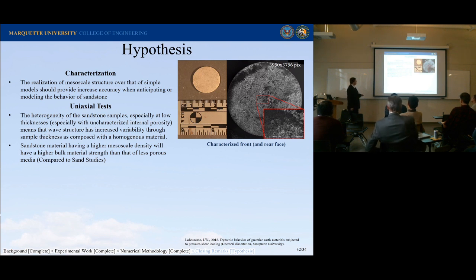I won't make it. And then finally, a sandstone material having higher mesoscale density will have a higher bulk material strength than a less porous media. So we'll see if that's the case as well. If I can do enough pre-characterization, maybe I can see that there's a porosity-strength relationship. But it'll be a lot easier to do than something like sand, where it's harder to control your porosity. At least I can pre-characterize to some extent.